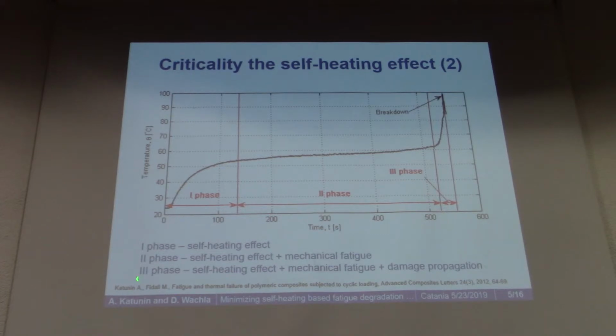apart from the self-heating effect, so the viscoelastic induced heating, we have additional frictional heating here due to the friction of surfaces in the crack. So of course it ends with the breakdown or failure of the structure.